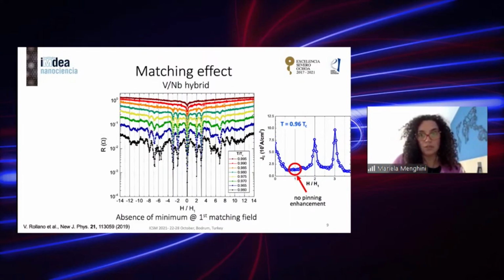Okay, so what we did first was to look at the matching effect, so these magnetoresistance curves as a function of temperature. As we lower the temperature, we start to see these minima in the resistance that increase, of course, the further you go down in temperature. But the interesting thing here is that we have normalized by the matching field, and we don't see a minimum resistance at the first matching field, right? And this is, of course, consistent when we look at the critical current as a function of field, and we don't see this enhancement that is usually observed at the first matching field.